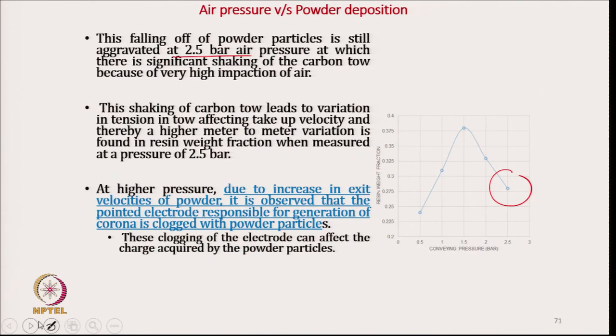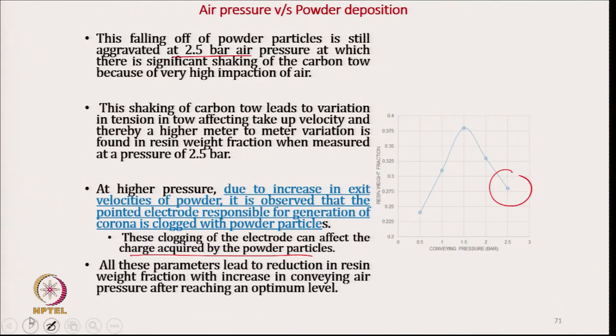At higher pressure, due to the increase in exit velocity of the powder, it is observed that the pointed electrode responsible for generation of corona gets clogged with the powder particles. This clogging of the electrode can affect the charge acquisition by the powder particles. If it clogs, then the charging will not be proper. So, all these parameters are responsible for the reduction in resin deposition beyond a certain level of conveying pressure.